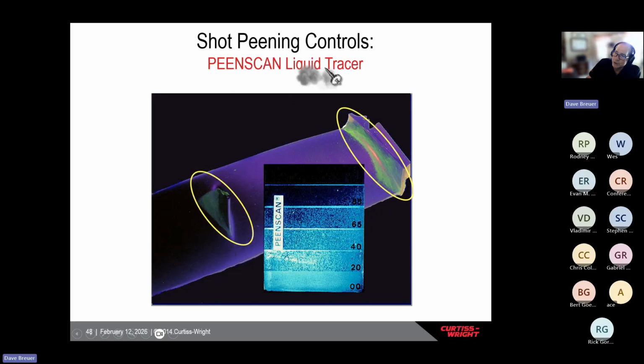So we have a liquid tracer dye. When you apply the dye, you let it dry, and under a black light, it shows up as greenish white. When you see solid dye, there's no shot peening coverage. As you increase shot peening coverage, each impact is removing the dye, so as you get more coverage, more of the dye is gone. This is about 65% covered, 85% covered. And then this has 100% coverage right there because all of the dye has been removed. So we use this dye for setup purposes.